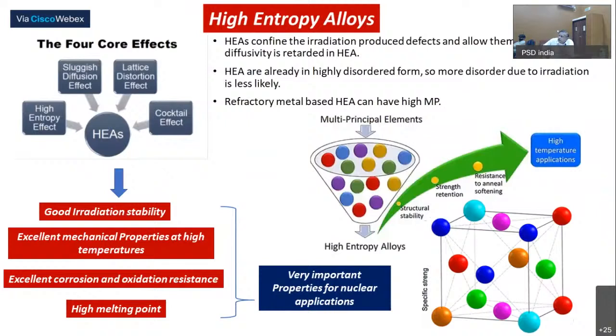So what can we do in turn? If we have a high entropy alloy, because of the very distorted lattice and sluggish diffusion, neither interstitial nor vacancy can move, and there is a chance of recombination. So the property will not deteriorate as it does in conventional alloys. Okay, so this will improve the properties, at least from a nuclear point of view, at least in concept. We have to show this on an experimental basis.